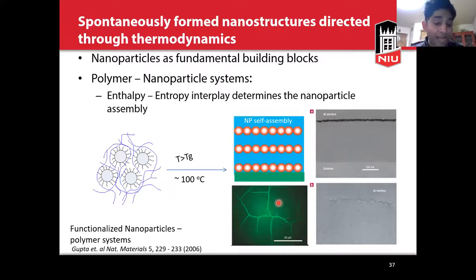or in this extreme example, where you have a coating with cracks, and you drive these nanoparticles to actually fill the cracks through self-assembly, through thermodynamics. Basically, you provide them with the right conditions, and these nanoparticles can be driven to fill the cracks and heal that cracked surface. So in future, this may be a possibility where you have a scratched paint on your car, and all you have to do is just apply some air dryer on there, and then that will basically self-heal. But that's a possibility in the coming future. That's what at least these scientists wanted to demonstrate in this example.